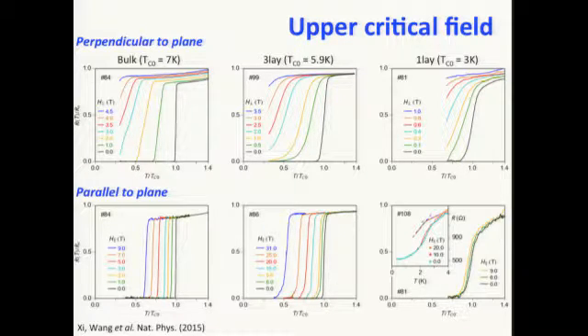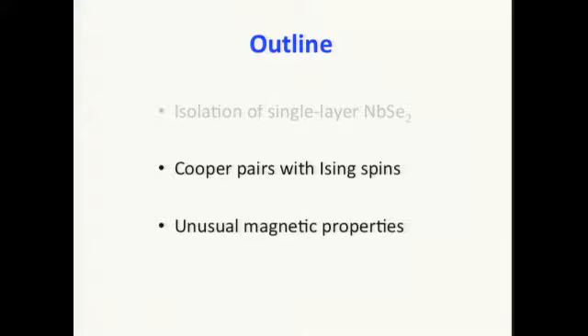And it survives up to 20 Tesla very well in the monolayer superconductor, even though the TC is very low, only 3 Kelvin. So the magnetic field that the superconductivity still survives is much higher than it should be. And I will explain what I mean by it should be. I'm going to spend the rest of the talk on this observation. I will explain it in terms of the spin-orbit interaction in the material, the Cooper pairs with this kind of effective Ising spins. And I will also talk about some signatures of the spin-triplet component of the Cooper pair wave function in our most recent measurements.